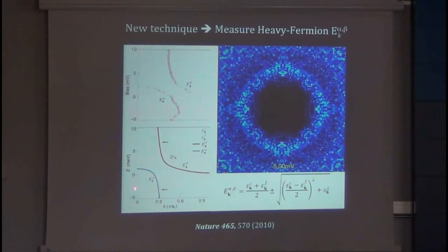Heavy band structure, the wave vector as a function of energy, should be something starting at a large radius, moving to a small radius, jump to a large radius, and move back to a small radius. These are the data from the movie I just showed you, and they're in excellent agreement with this theory. And in fact, this was the first time that heavy fermion wave functions were visualized directly. And that has opened a door very wide now. If you look in the literature, you'll see that there are dozens, if not hundreds, of people trying to do this now to study exotic heavy fermion compounds.